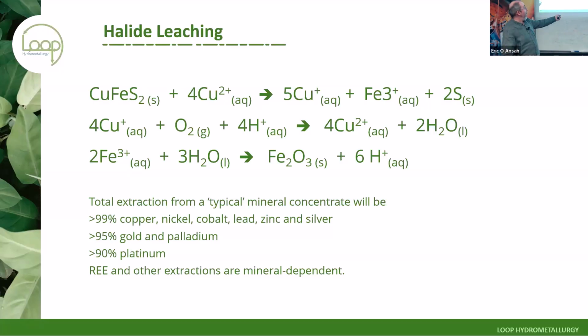And we regenerate cupric. The iron hydrolyzes with water to form hematite. When you add those 3 reactions together, effectively what you have is the copper catalyzed reaction between mineral and air. So your primary reagent in your process is plain old air. The only thing that's coming out of your process is spent air, using about 5% of the oxygen that's present.